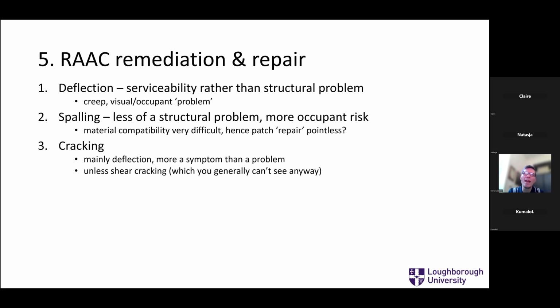Cracking, again, mainly cracking through deflection is what you see, and that's not really an issue. The shear cracking is the issue, and that's on the side of the planks, and you can't see the sides because they're next to each other. And if you're seeing shear cracking, sometimes it's too late because it's starting to fail in shear, and it's a bit too late.